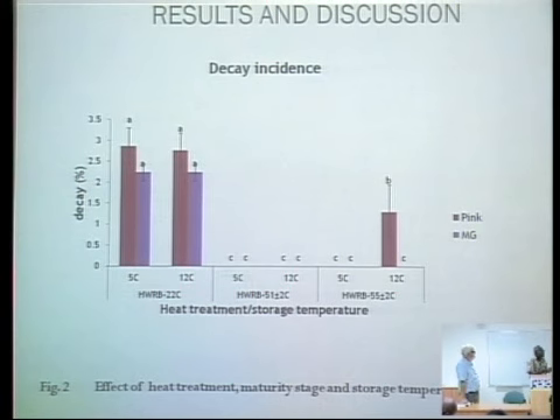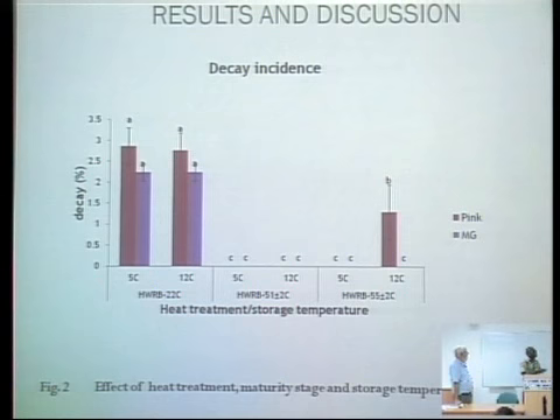And the reason why we didn't have any chilling injury at 5 is that there's a heat shock protein in the fruit, which when expressed as a result of the thermal treatment is able to inhibit the injury, especially at this temperature. So we believe that the heat treatment probably induced this gene, which is responsible for inhibiting chilling injury, to be expressed more in heat-treated fruit, and so we were able to inhibit the chilling injury.